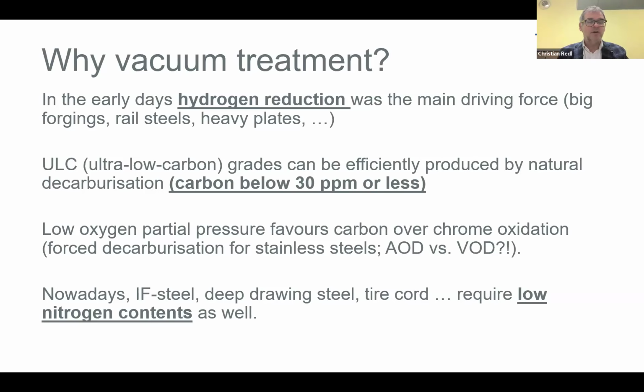Of course, if you are going to produce a majority of only stainless steel, you might go for the AOD, and if you are also producing some kind of tool steels or a mixture of steel, then you do a vacuum treatment like a VOD, vacuum oxygen decarburization. And nowadays, a lot of steel grades like interstitial free steel, deep drawing steel, and tire cord require nitrogen contents as low as maybe 30 ppm as well.